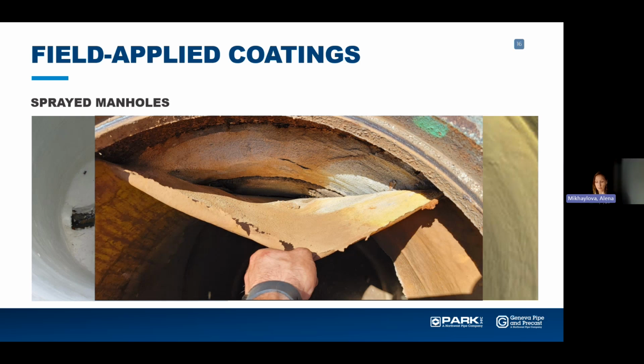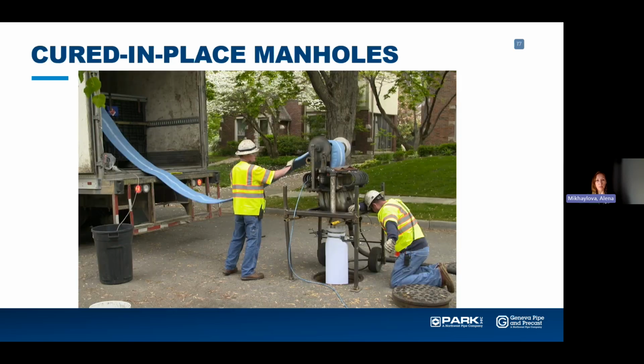Of course, with time, newer spray liners are becoming more advanced, and you can spray much faster to achieve the thickness. They dry much faster in between the layers. So maximum life of coatings can be anywhere between 2 years, from what I've heard from the feedback from agencies, all the way to 10 or 15 years. But on average, the failure that we're hearing happens in the applied coatings is about 5 to 7 years, where you have to go back and reapply. So, another example of failure of coating: it delaminates from the wall.